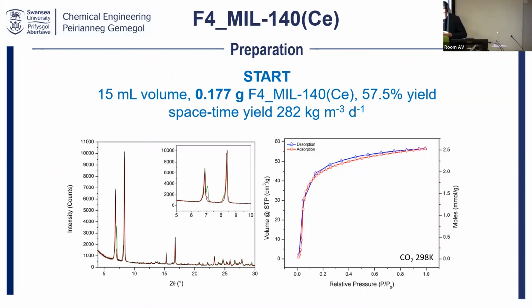This one you saw on the left-hand side. I would put you to sleep if I just talked about this, but it's an X-ray diffraction pattern. What I would like you to do is try to memorize how it looks. And on the right-hand side, an important part of the characteristic of this material is that at different pressures of CO2, the material captures CO2. So the fact that this curve goes up shows that the material is able to absorb CO2, and it goes up to about 10% of its weight.